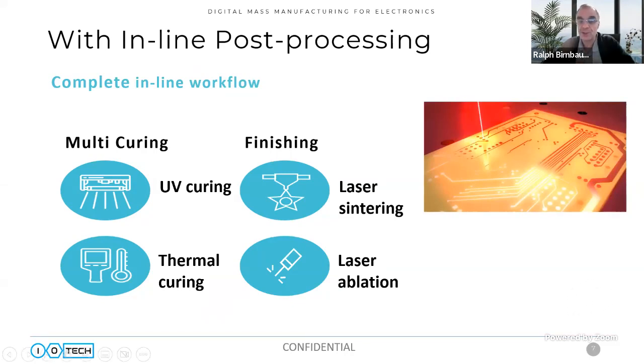There is also place in the machine for post-processing. So we can also add a UV curing or a thermal curing station within the machine. This will be especially helpful for any kind of additive manufacturing application, if you want to do multiple layers that require some kind of curing in the middle. For metal pastes, the same laser used for the CLAD can also be used for the sintering. And also any excess material can be ablated away with the laser.